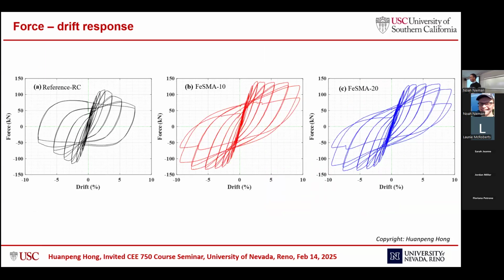Here's the force drift response of the 2 columns we measured compared with the reference RC column. The red one and the blue one are the columns we tested, and the black one is the column with exactly the same design, material properties, and dimensions. So we are making comparisons among them. From this curve, we see that the 2 iron SMA columns exhibit higher strength, and also after unloading from the same applied drift, their residual drift is much smaller than the reference RC.